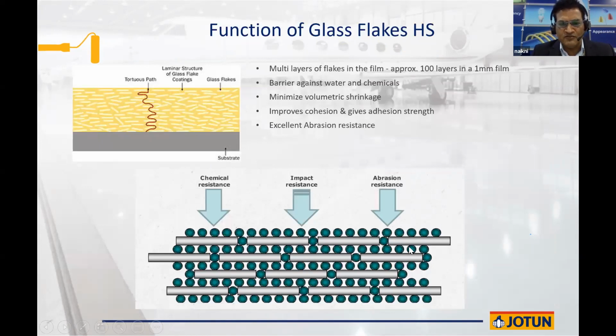If you take a cross section, this is what it looks like. Basically, the glass flakes, which look like fish scales in a way, are reinforced in an epoxy resin. So when it's reinforced in this epoxy resin, once it cures it provides a barrier layer which provides excellent chemical resistance, impact resistance, and abrasion resistance. Approximately, you have 100 layers of glass flakes in 1 millimeter of DFT coating. So if you apply a 300 micron membrane on a car park, you have about 30 layers of reinforcement of the glass flakes. So it's a very robust kind of protection that you provide to the car park.